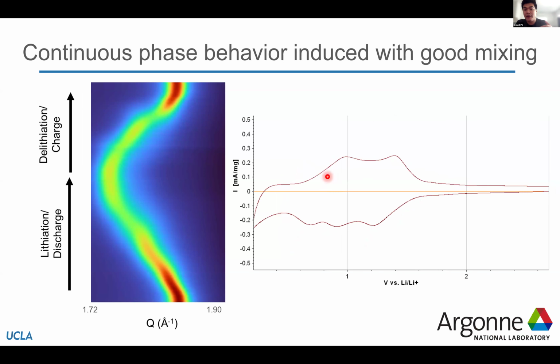And then in the case where we have a more well-mixed material, we can see that there is a single phase reacting in a smooth, continuous manner. And so in this case, we have suppressed the discontinuous phase transition, and that can be interpreted as allowing the material to expand at all of these spacings without the need to nucleate and grow a new structure. And in this case, that's aided by the larger tungsten atom essentially pre-expanding your material so that it is more accommodating of lithium in the first place.